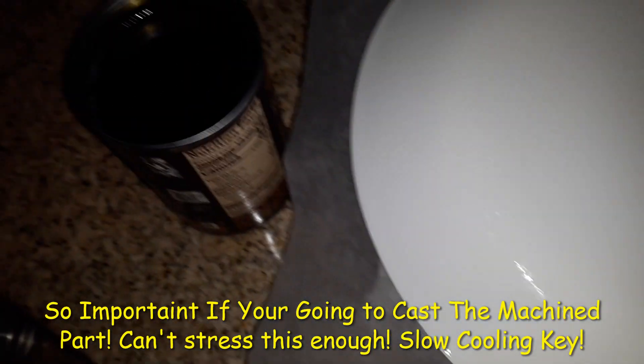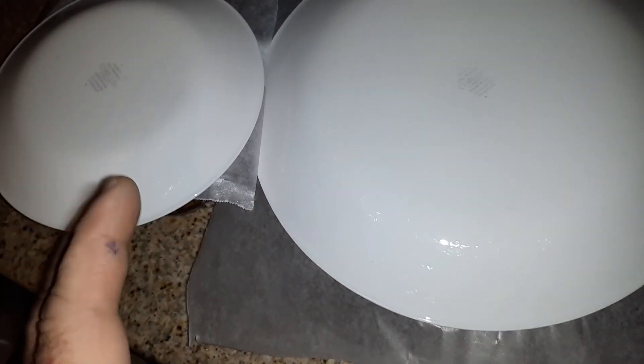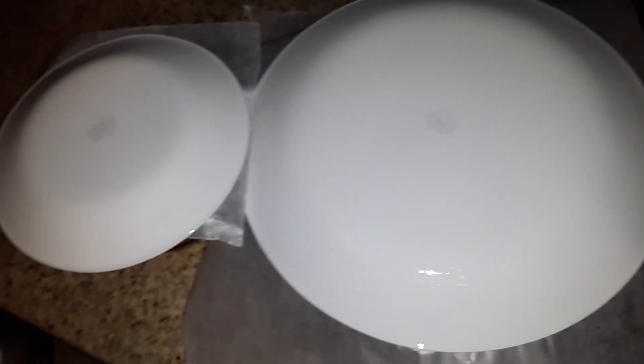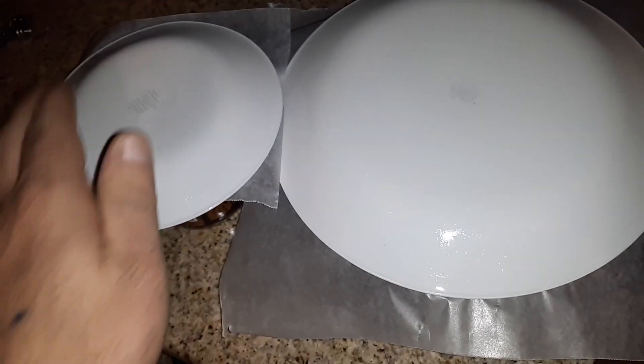I want to show you something. You want to take a piece of wax paper, put it over your mold, put a board, a plate, something, and you want to retain the heat. This stuff is food-grade plastic and just paraffin, so it's safe. You want to heat it to about 180 degrees to get it melting and keep it at around 190. You'll need a thermometer — let it slow melt until you get it like syrup. That's when it's ready to pour. If it's steaming, smoking, or sputtering, it's way too hot. You want a nice, even, slow melt.